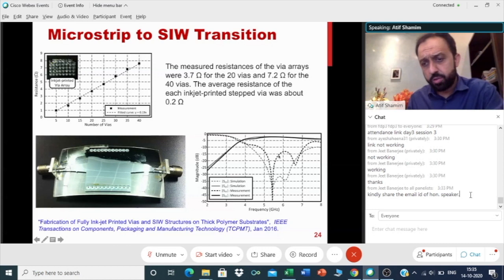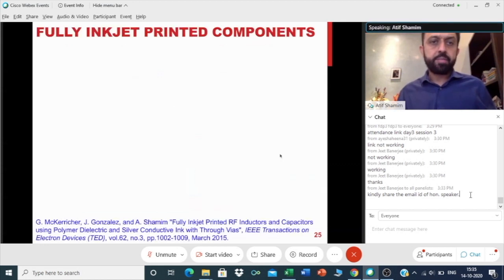And then the transition worked very well. And then we did a bunch of filters and antennas on that technology, using those vias. Now, I have shown you so far only printing of metal, right? But in order for us to fulfill that dream of having fully printed systems, we also need to print the dielectric, or the substrates themselves.